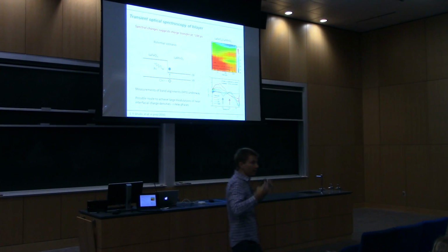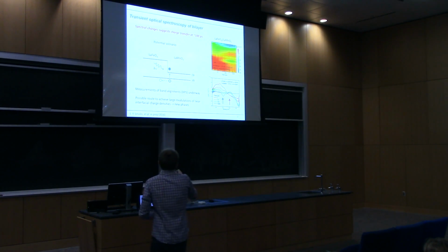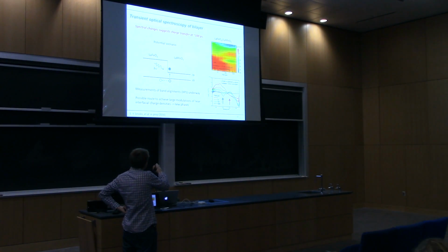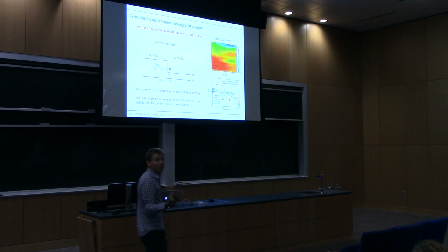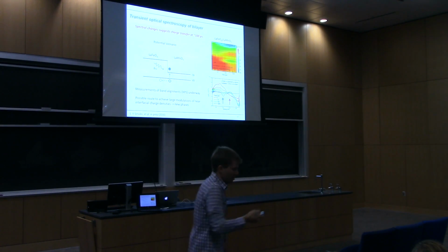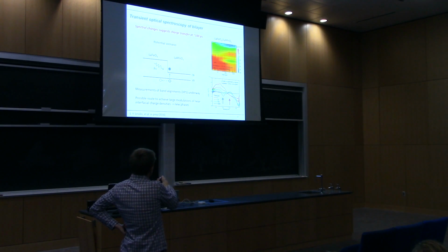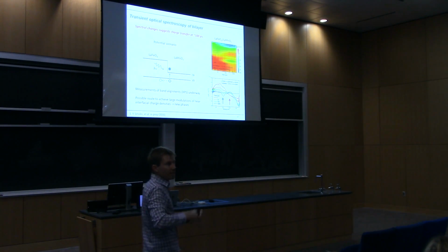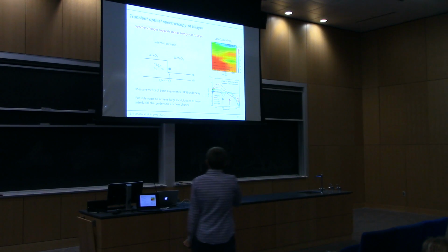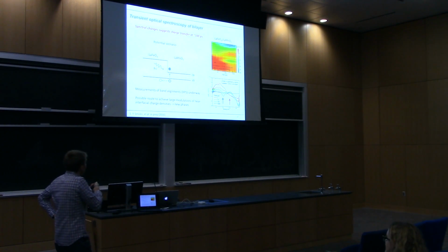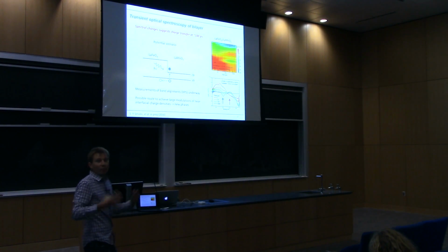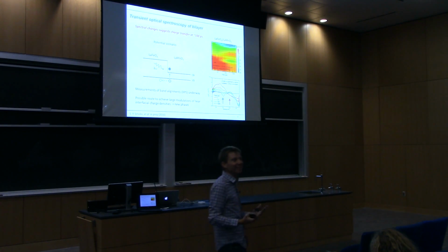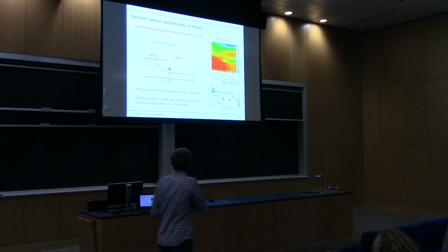So a scenario that can fit this data is that we're coming in with light, exciting within the lanthanum manganite. We excite this electron, it has this smaller gap, and the electron gets stuck here. But if these valence bands are lined up correctly, this hole can migrate over to the LFO, and that can lead to a bleaching feature in the lanthanum ferrite. It takes on the order of maybe 100 picoseconds for this hole to migrate over, because mobilities in perovskites are relatively low. Really, to nail this down, we need measurements of band alignments. I can draw this in PowerPoint, but is it the real, actual band alignment? And so XPS measurements are underway.